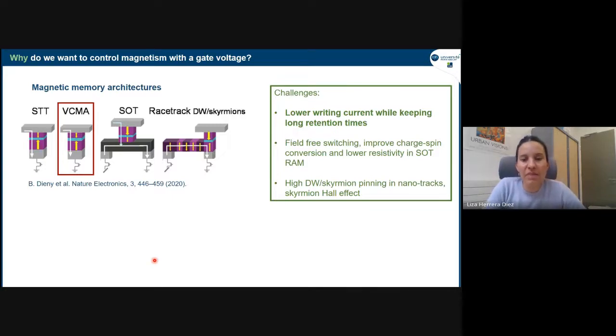So the challenges are to lower the writing currents that we need to write information while keeping long retention times. That means that we want to be able to write information on a state that has, let's say, a relatively low energy barrier, so it wouldn't cost too much energy. But at the same time, you don't want this energy barrier to be too low, so that it starts competing with thermal activation, because then your information is going to just die out. And we want to have this very strong and robust magnetic memory. So we need a compromise between those things.